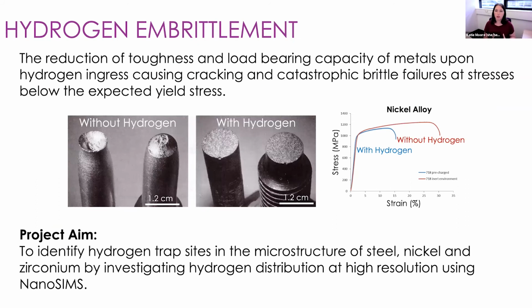So what I want to focus on for this particular seminar is how we've been using the NanoSIMS to look at hydrogen embrittlement. I'm sure a lot of you are aware, but just to briefly go through it, hydrogen embrittlement is where we get a reduction of toughness and load-bearing capacity of a metal once we get hydrogen entering into it at significant concentrations. And that hydrogen can cause cracking and catastrophic brittle failure of that material at a value that is much less than the expected yield stress.